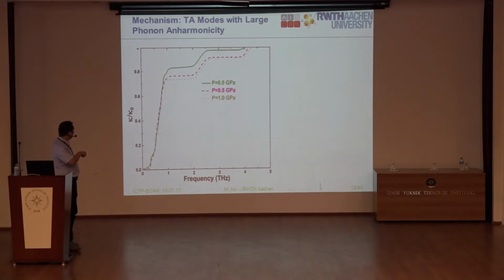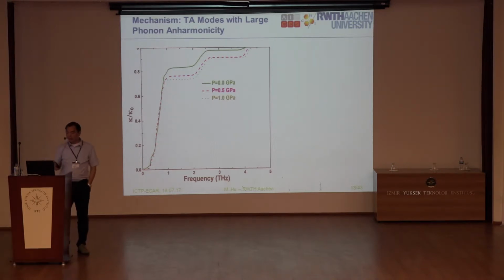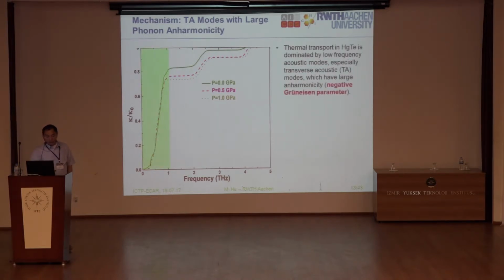First we have to calculate the thermal conductivity as a function of frequency, so we know the major heat-carrying phonon modes in mercury telluride. If you plot this, you'll find that the majority of the heat is transported by low-frequency acoustic phonons. That's also understandable, right? And the detailed analysis shows that the majority of phonon transport is contributed by the transverse acoustic modes, the TA modes. And then we also have to link these transverse acoustic modes with the negative pressure dependence, right?